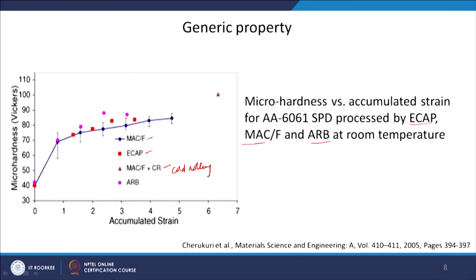If you see all these 4 processes, they are nicely following one kind of generic behavior: if the accumulated strain in all these cases is the same, the effect on micro hardness or mechanical property is the same. They will all contribute to the hardness in the same way. So, it does not depend on which route you are putting strain into the material. Their contribution to the hardness or mechanical property will remain the same. And we have also seen that when the strength is increasing, the elongation to failure or ductility is decreasing, which is also true for all the processes.